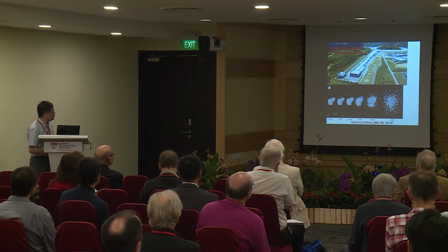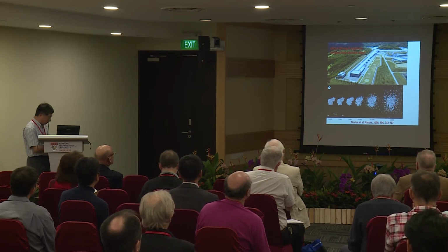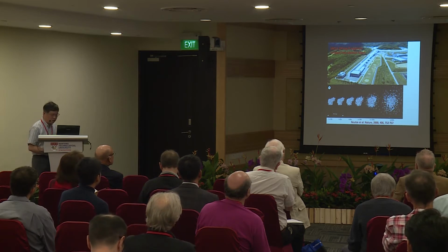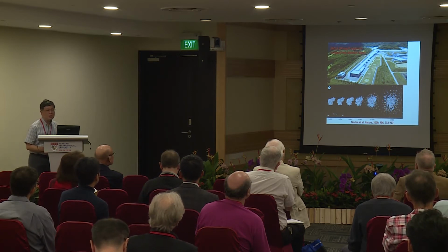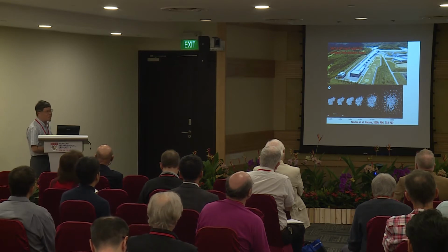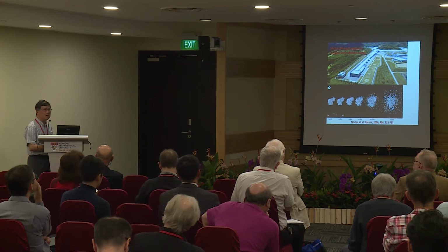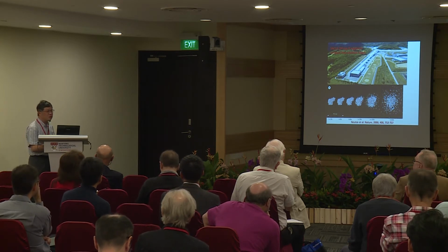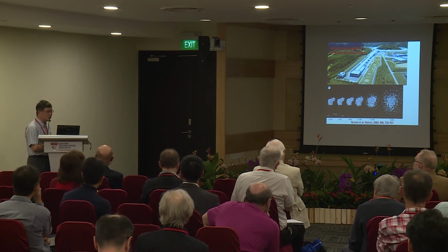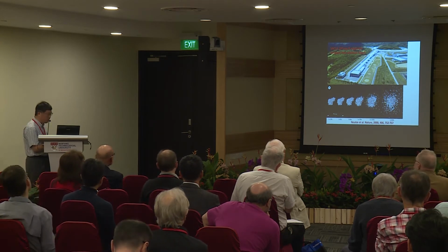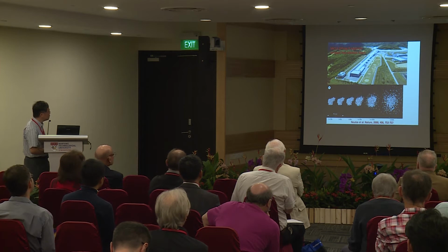So in order to remove the radiation damage, we performed X-ray diffraction experiments using the XFEL, X-ray free electron laser, which has a pulse duration of 10 femtoseconds. And within these 10 femtoseconds, the structure changes caused by the X-ray radiation will still not occur. So we can collect data before the structure is changed by the X-ray radiation damage.